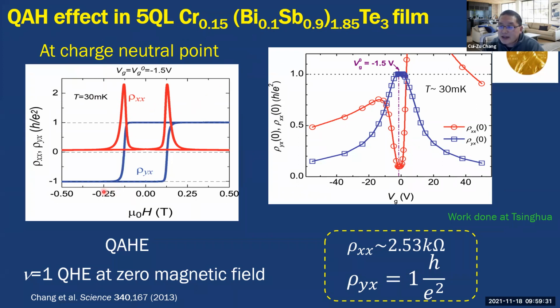Here, we can see the magnetic field dependence of Hall resistance and longitudinal resistance. At 0 magnetic field, the Hall resistance is quantized and the longitudinal resistance is close to 0. And if we plot the 0 magnetic field Hall resistance and longitudinal resistance as a function of the gate, we can see that at the charge neutral point, the Hall resistance is quantized and the longitudinal resistance shows a dip here. It's still not 0, it's 2.5 kilo ohm. It's not completely dissipationless transport, but this observation marks the first discovery of the quantum anomalous Hall state in the magnetically doped topological insulator system.